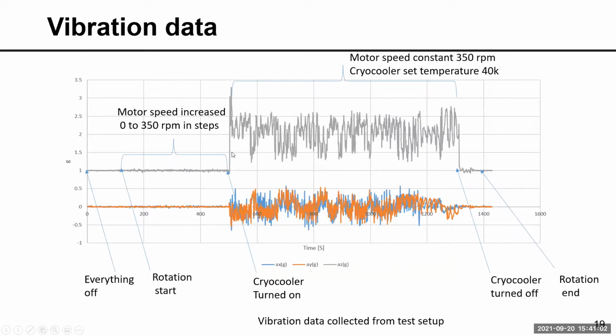However, we also observed a huge vibration coming from the cryocooler. For example, here everything is off, and then here the whole setup is running at 350 RPM. Then here we turn on the cryocooler, and you can see that once you turn it on, there's a huge vibration. This means that if we attach the cryocooler to the rotor, this vibration will be translated to the field winding. We can use some thermal straps to avoid the vibration going to the winding, but this can be addressed further on, when we hit 350 RPM, and see how we can avoid it going to the actual field winding.